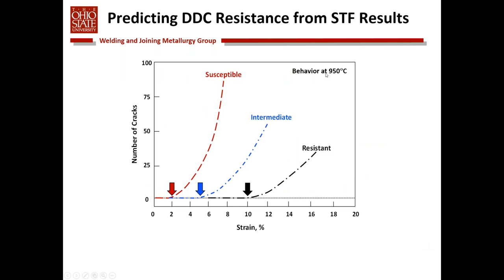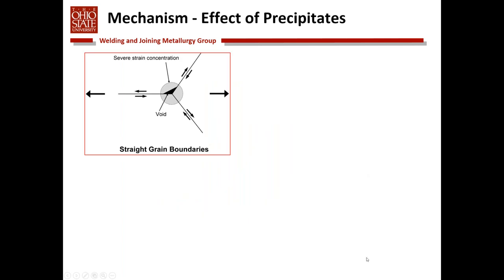Plotted in a different way, if we look at behavior at 950 degrees C, if we start to get cracking at 2% or less, then we deem the material susceptible. It's intermediate if cracking starts at slightly higher strain. And if we have materials that do not crack up to about 10% strain, we know that they're very resistant to this form of ductility dip cracking. So a lot of filler metal development has been done, and the DDC resistance has been tested using this particular test.